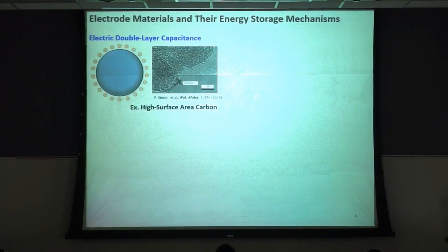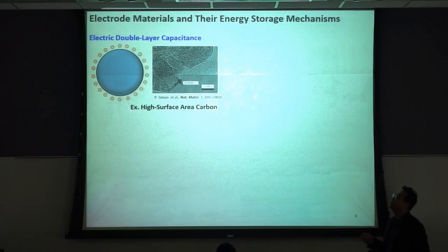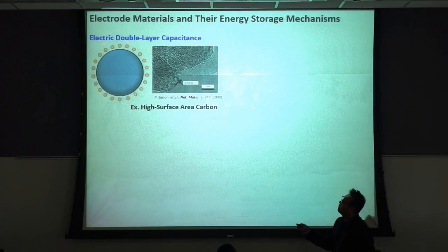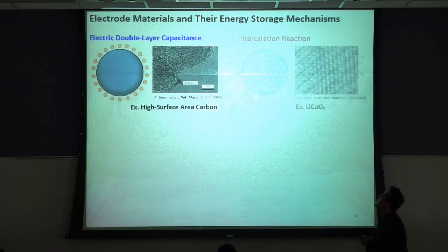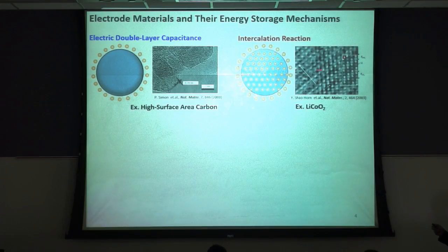So then, if I further explain the electrode materials and their energy storage mechanisms, this is a double layer capacitance. Let's say this blue circle is the electrode material, and these orange dots are electrolyte ions. During the charging, they can adsorb on the surface of electrodes. As I mentioned, this is a double layer capacitance. To maximize this double layer capacitance, we use high surface area carbons. On the other hand, for the intercalation reaction, lithium ions can penetrate into the bulk of materials. Basically, we fully utilize the electrode materials. An example is layered structure lithium cobalt oxide.